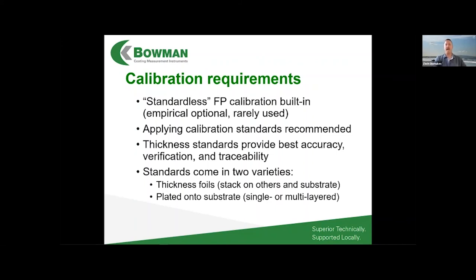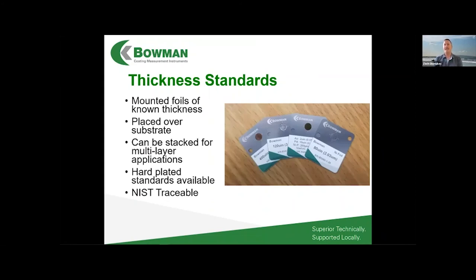In other cases, some people prefer to have an actual plated standard, where in the same scenario, you would have gold plated on nickel plated on a piece of copper. That standard would be a closer representation of the actual plated material, because it is plated, but also it's more robust. These foils, as I'll show you here, are pretty thin. You can imagine a foil that's a few nanometers thick, you sneeze on it and the thing blows up. So sometimes they're so thin you actually have to have a piece of mylar or something transparent to X-rays on the back of it to give it more strength, because it's such a thin, weak foil. So again, these can just be stacked on top of each other.